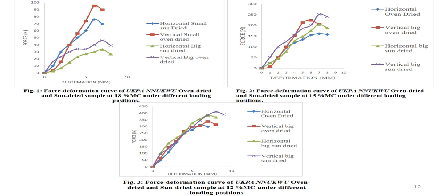By looking at these graphs, you're able to know the trend and what happened inside the seed sample during compression. You see the trend with dark red color, which is small African walnut, oven dry, loaded at the vertical loading position, displays and recorded the highest cracking force, followed by small size walnuts, sun dried, loaded at the horizontal loading position. Then the third were big oven dry walnuts loaded at the vertical loading position. The sample under 18% moisture content that requires the lowest force to be cracked is the big sun dried African walnut at horizontal loading position.